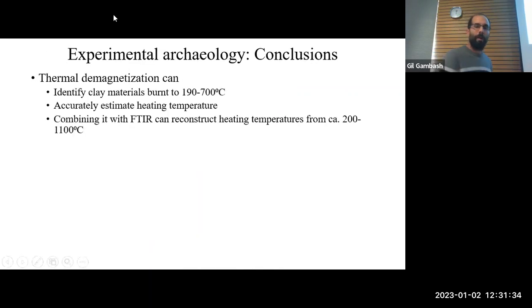So this is very important. And as I said, there's no other tool that deals with these low temperatures that does this. But FTIR, I didn't mention this before, has a great advantage in the higher temperatures. With archaeomagnetism, you cannot say anything about the temperatures when it's more than 600 or 700 degrees. You can only say it was heated to higher temperatures, but you can't tell what these temperatures were, because of the mineralogy of the magnetic carriers. But FTIR sees the changes in the mineralogy also at those high temperatures. So if you want to estimate temperatures in a wide range from 200 to 1,100 degrees Celsius, you can use archaeomagnetism for the lower temperatures, and FTIR for the higher temperatures. So the combination gives us a very good tool.